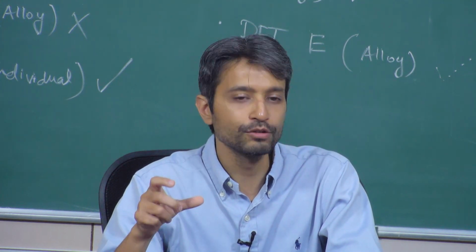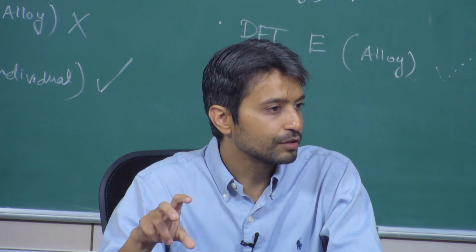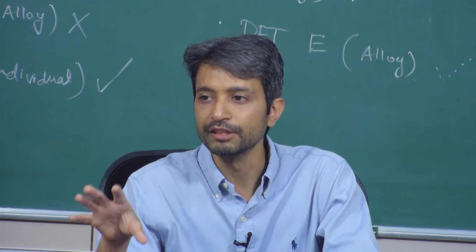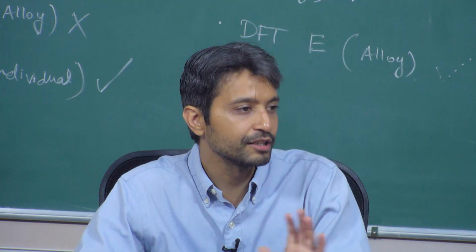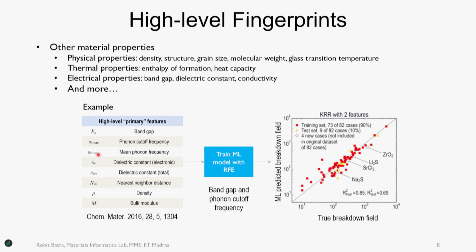Now, if you know this mechanism, then you know it is important to talk about phonons, it is important to talk about electrons, their kinetic energy, band gap. These are the important features associated with the mechanism. Once you understand that, you will see that these authors have considered properties related to that mechanism. For example, they talked about band gap. The larger the band gap, the more difficult it is for electrons to have high kinetic energy. There won't be any free moving electrons. Phonon related frequency, so phonon electron coupling. These are the things you need to talk about to capture this phenomenon.